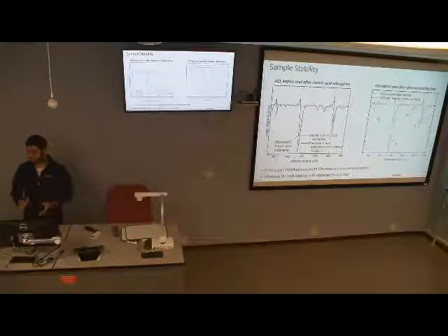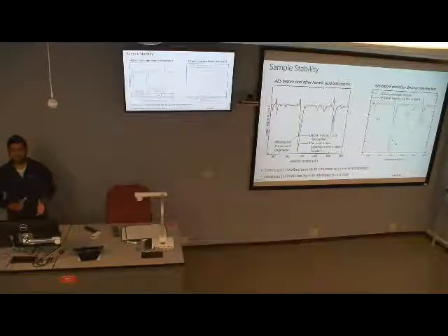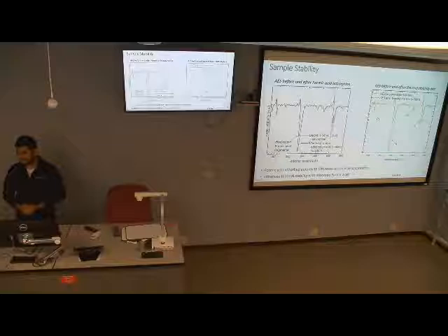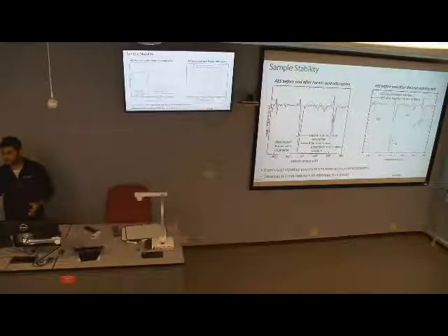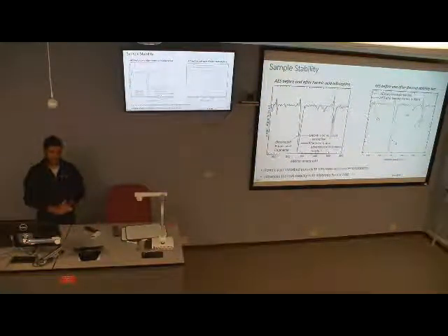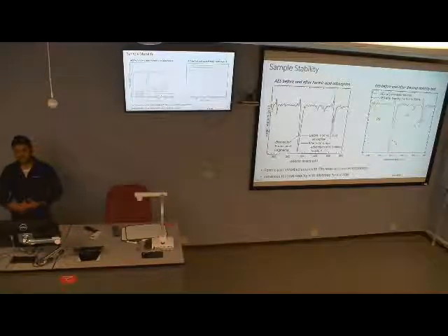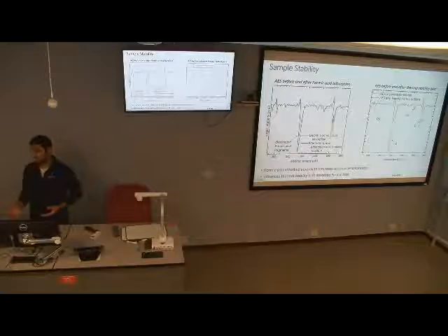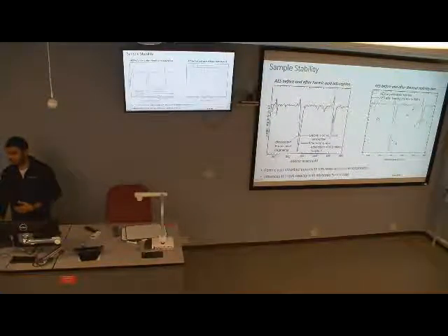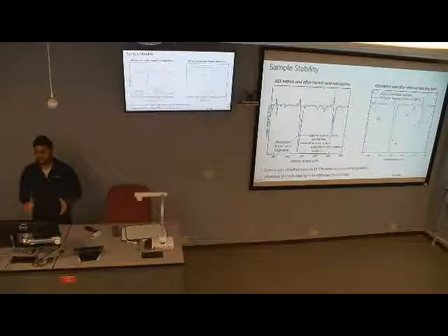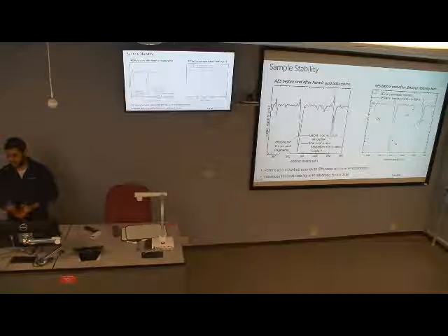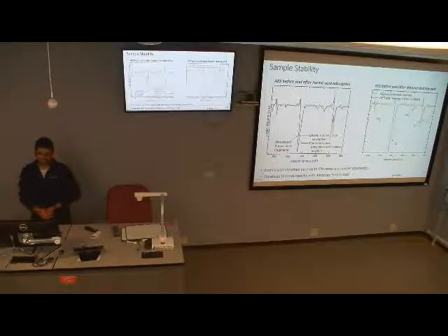And we did similar thermal ramps with a bare perovskite film without the adsorbed formic acid layer. So when we heat those perovskite layers without the formic acid adsorbed layer, the perovskite structure seems to be destroyed after those thermal ramps. So that means the adsorbed formic acid layer has introduced some kind of stability for this perovskite structure.